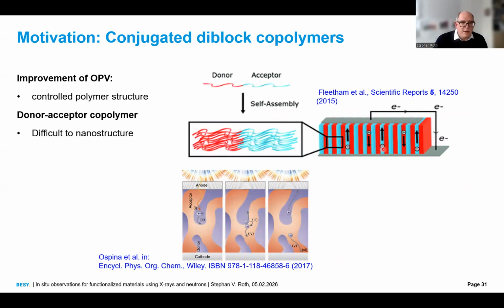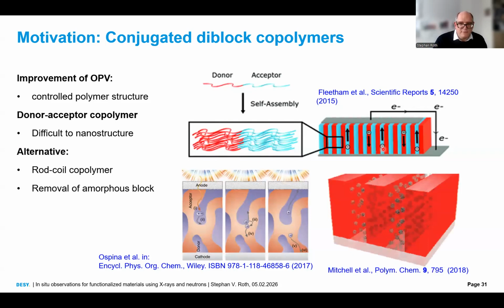Yeah, they are somehow difficult to nanostructure. You need to tune the right solvent. And especially what you can do is you can use these rod coil polymers with one of the conjugated polymers, P3HT, for example, and an amorphous PMMA block. And you can remove the amorphous PMMA block quite easily. And then here you have this standing lamella of the P3HT, and you can backfill this then, for example, with buckyballs or other non-fullerene acceptors.